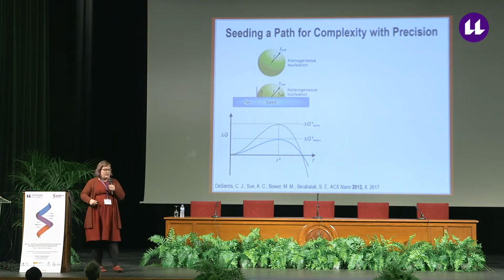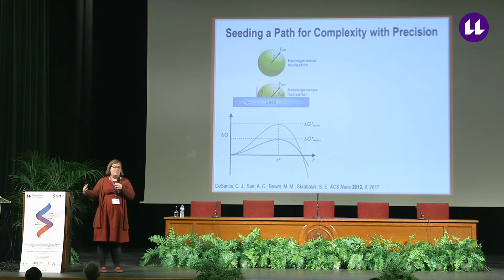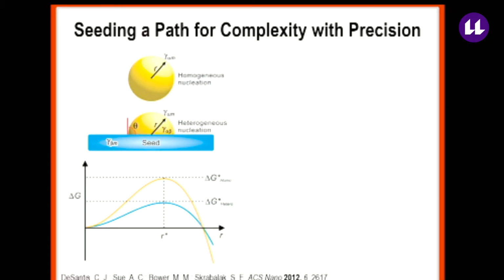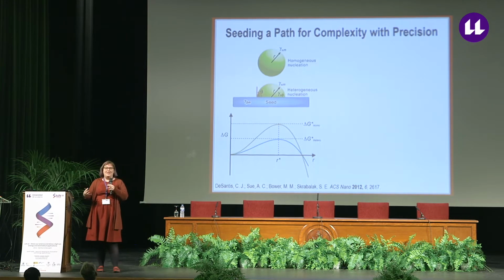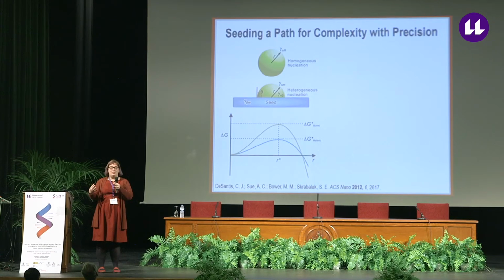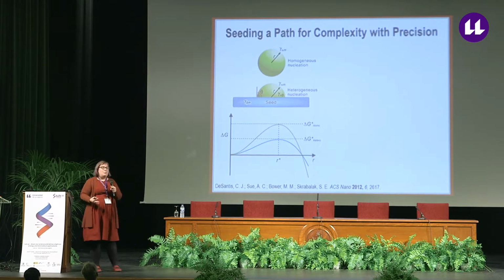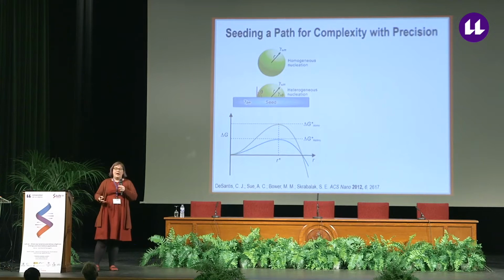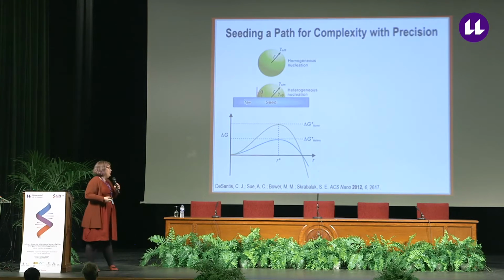and one of the ways in which my group has been trying to address this desire for more compositionally complex nanomaterials, but with structural precision, is to couple these co-reduction methods with seeded syntheses. So seeded syntheses are where you take some sort of preformed material and build on top of it. So in our case, we're taking preformed metal nanoparticles that can be dispersed in solution. We'll pick the very best syntheses from the literature that have size and shape controlled nanoparticles and try to build a more compositionally complex phase on top of those well-defined seeds.